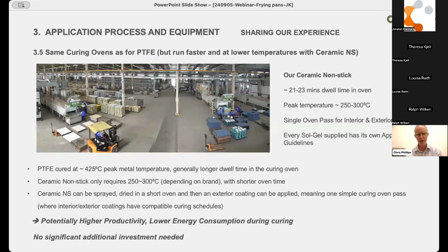The curing process, the ovens are exactly the same. Ceramic non-stick cures at a lower temperature, and generally it spends a shorter time in the oven. So that potentially will transfer into higher productivity. Your pans go through faster with lower energy used during the curing process. You can use your existing ovens, so no new investment needed. Next slide.